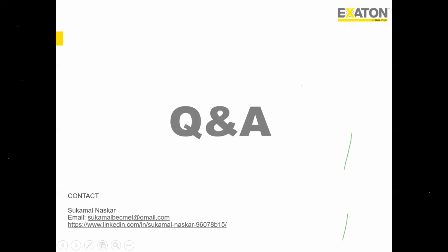Yeah, thank you. There is also a question on casting. How much nitrogen is preferred for the casting process? In casting, the raw material or base material has a lower amount of nitrogen compared to filler metal. If you are talking about, let's say, UNS 31803, you will have like 0.08 to 0.2% nitrogen. The nitrogen content usually ends up around 0.14 to 0.18% typically.